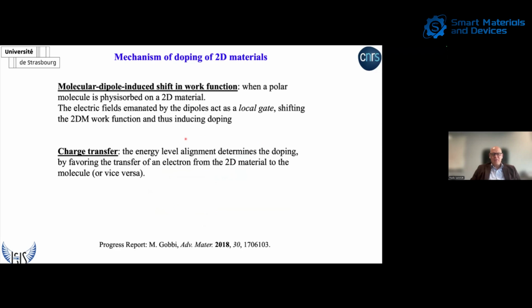And so there are two main mechanisms of doping two-dimensional material with molecules. The first one is a molecular dipole-induced shift in the work function. This can be obtained when you have a molecule with a high dipole moment, and you place this molecule on the basal plane of the surface of the two-dimensional material. And so it's the electric field emanated by the dipole that acts as a local gate and shifts the work function, and thus induces a doping of the two-dimensional material. Now, this effect can be maximized the more you are able to align individual dipoles.